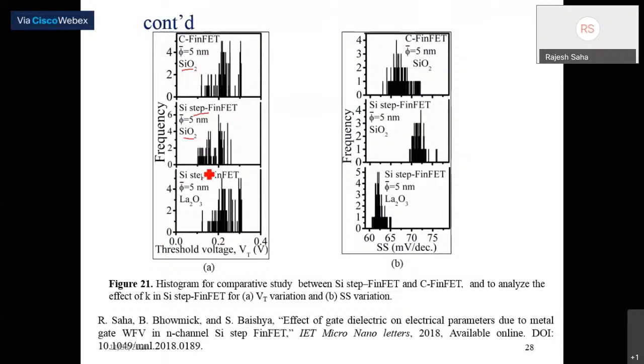As you can see, the variation in the threshold voltage is less in the step device compared to the conventional devices. Similarly, when you use lanthanum oxide as the gate dielectric, the variation in threshold is compared with SiO2. This is the SS variation. The SS variation is more in the conventional device compared to the step device. But using high-k, the variation in the subthreshold swing can be reduced.